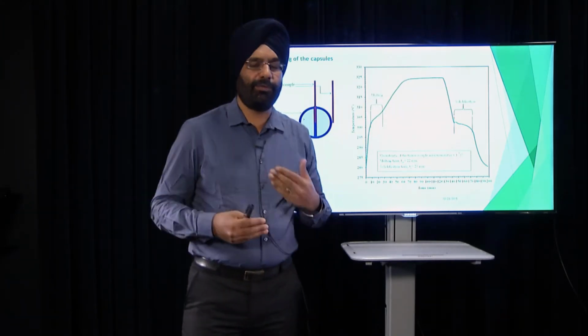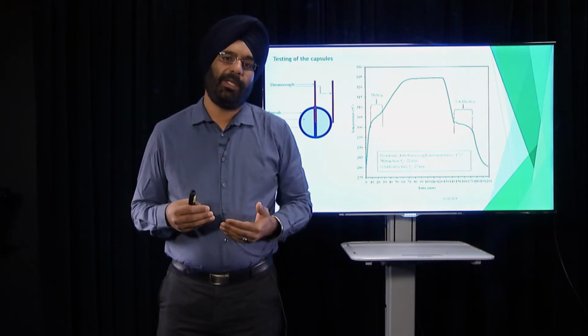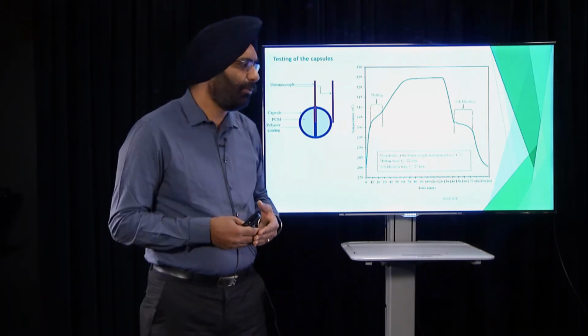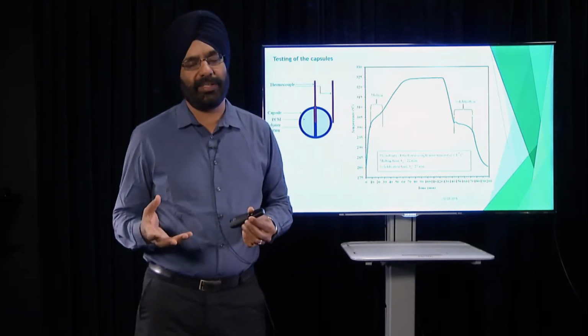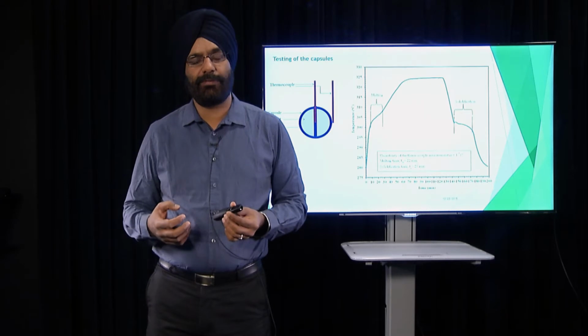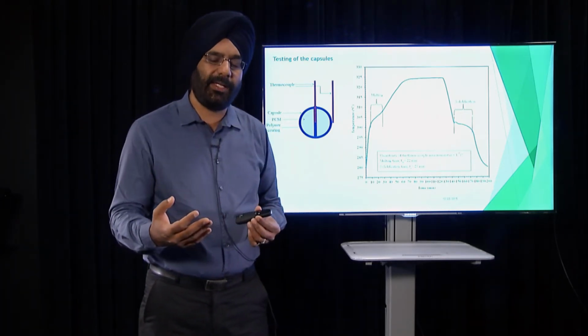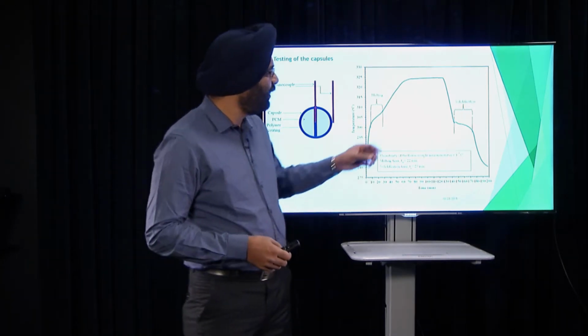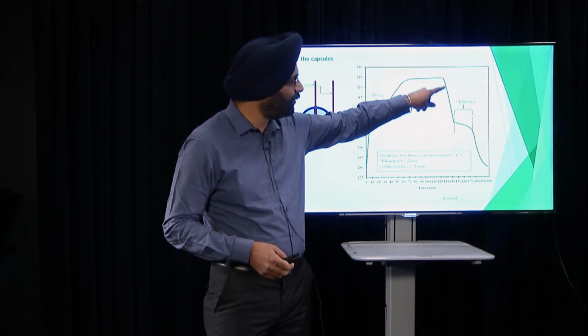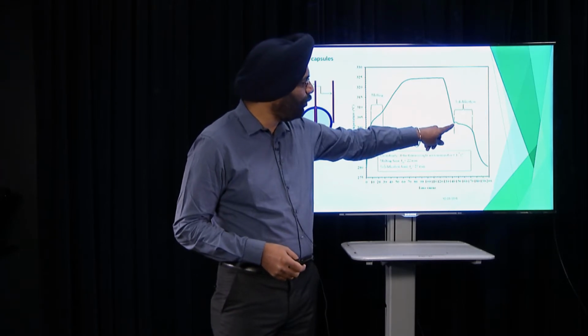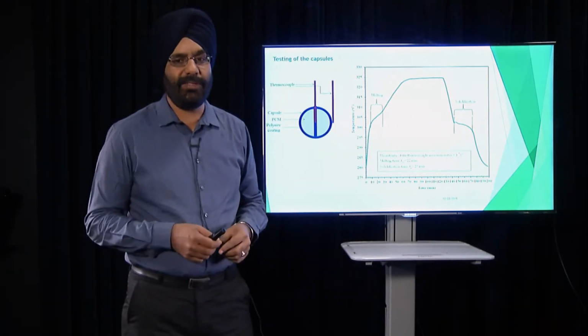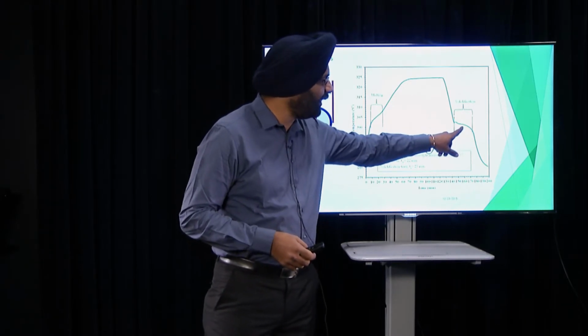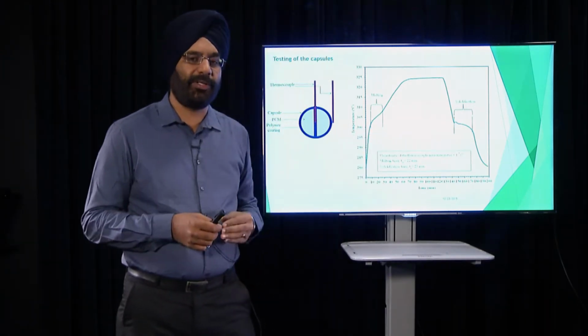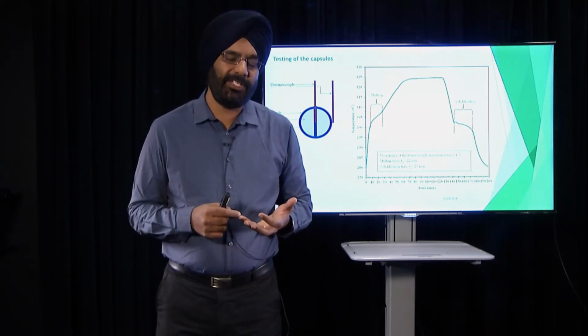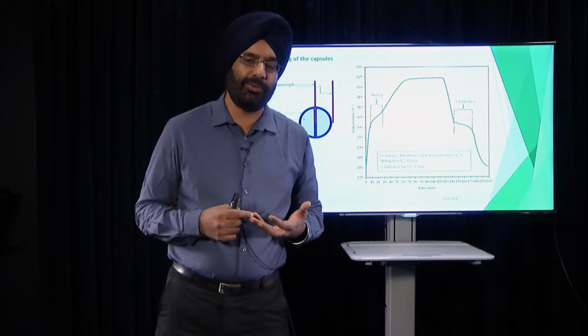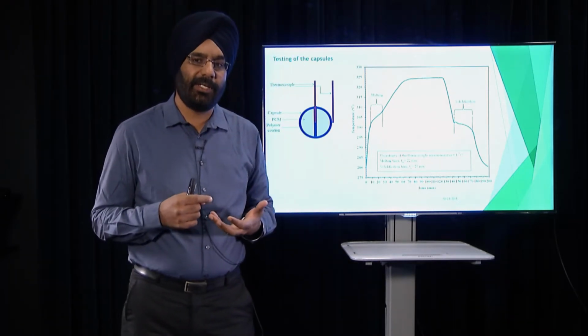After that, the flow was reversed. That means the temperature of the furnace was decreased. When the temperature of the furnace was decreased, the opposite thing happened. The heat is now being transferred from inside the capsule to the outside heat transfer fluid, which is air in this case. So when that happens, you will see immediately there is a tremendous decrease in the temperature, and the moment it reaches close to its freezing point, you will again see a kind of a plateau there, a flat portion. That's where the liquid phase change material starts getting converted into a solid. That's where it starts freezing.